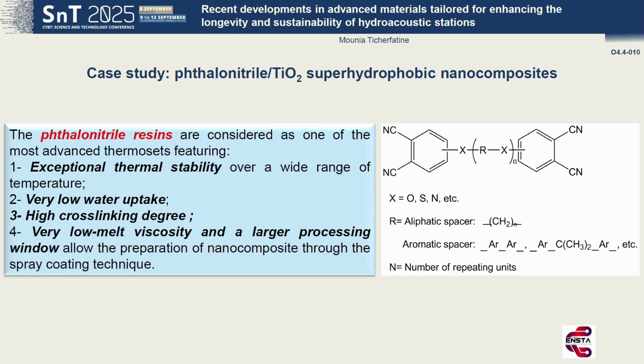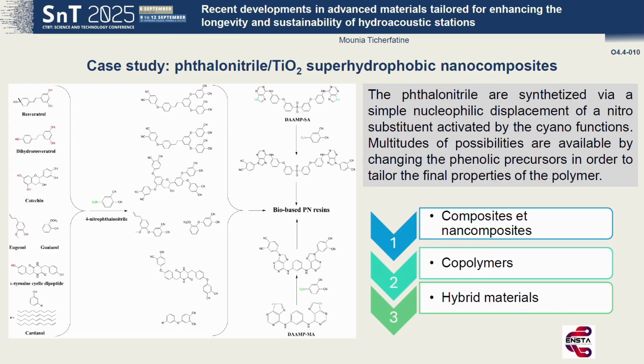The phthalonitrile resins are considered as one of the most advanced thermosets, featuring an exceptional thermal stability over a wide range of temperature, very low water uptake, a high cross-linking degree, and very low melt viscosity and large processing window, which allow us to prepare the nanocomposite through the technique of spray coating. The phthalonitriles are synthesized via simple nucleophilic displacement of a nitro substituent activated by cyano functions. Multitude of possibilities are available by changing the phenolic precursor in order to tailor the final properties of the polymer.